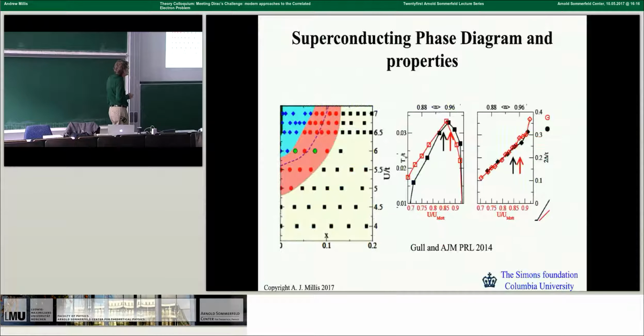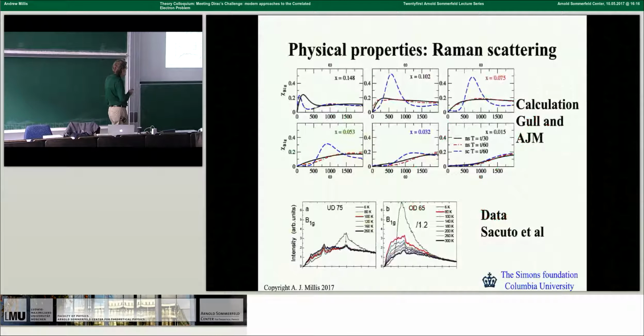All right? You can calculate the phase diagram over a range of U's. You can compute physical properties. You can compare them to experiment. This is one of my favorites. It's Raman scattering. What you see as you go from so-called overdoped to underdoped is a change from normal state to superconducting state, where you get a big peak in the Raman scattering spectrum in the superconducting state, that's here, to underdoped, where you see a suppression with temperature in the normal state and a weak peak at much higher frequencies in the superconducting state, that's this.